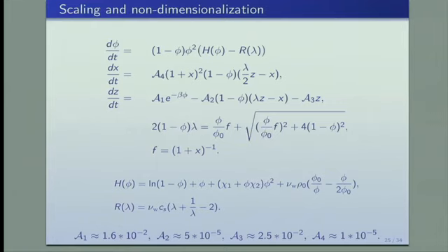However, it's very important to bring all of them back if you want to write a Lyapunov function, which I did at some point. Then you can immediately see that we have a gap in time scales. In other words, the mechanics, this elasticity equation, of course dissipative, with no inertia, is a lot faster than the chemical reactions. And I use this in the analysis.